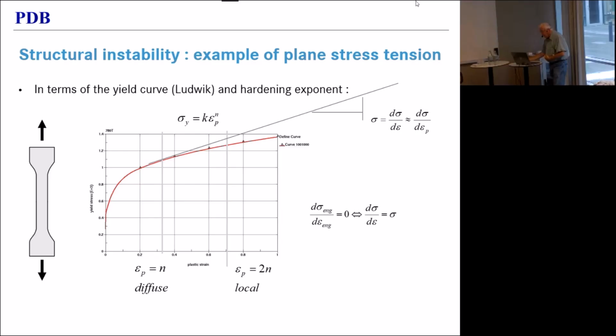Now we can look at that in terms of yield curves. The condition that you have a maximum in the force displacement curve is the same as saying that the tangent modulus is equal to the true stress. If we then neglect the elastic strains, we can say for metals with a good approximation that diffuse necking starts when the hardening modulus, the derivative of the yield stress with respect to the equivalent plastic strain, becomes equal to